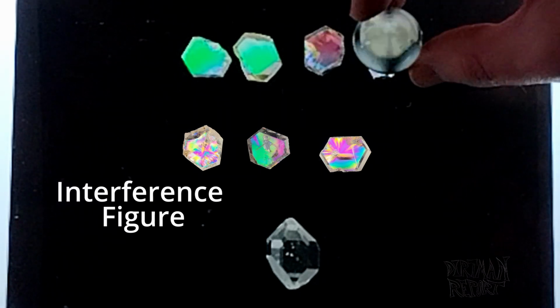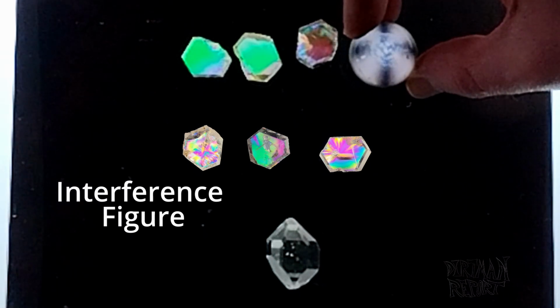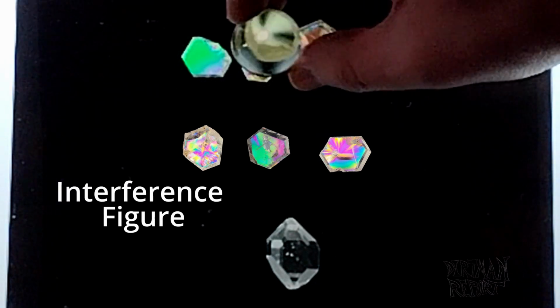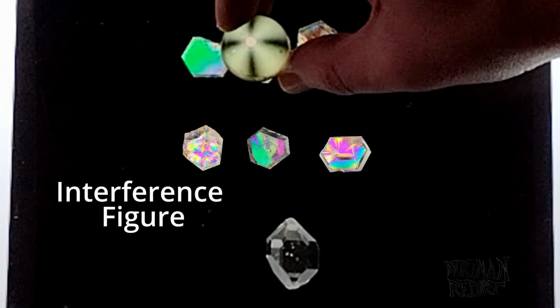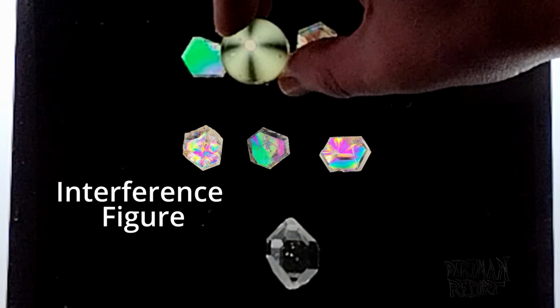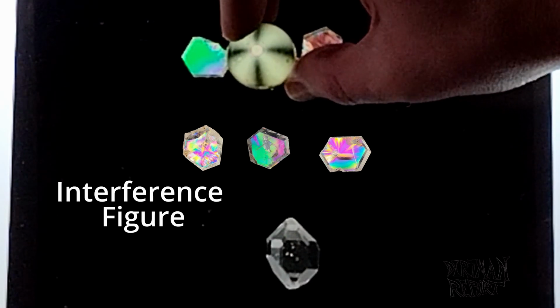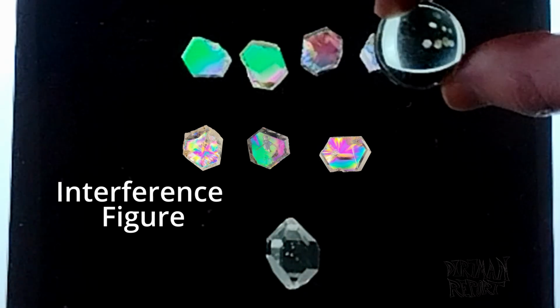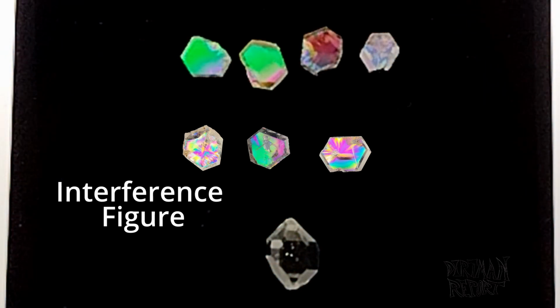So if you see in our very twinned amethyst, that figure is all sorts of messed up. If we take a look at our less twinned citrine, you see a nice circle in the center there. This is telling me that this is quartz in particular. This is a result of a property called optical activity.